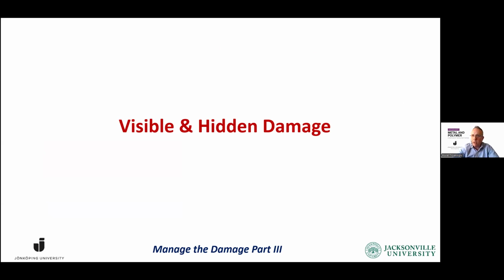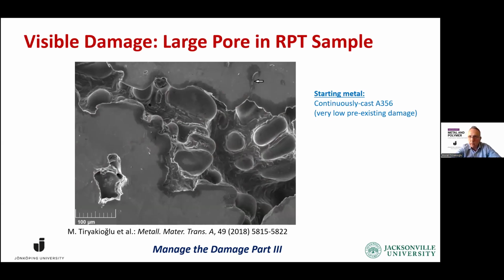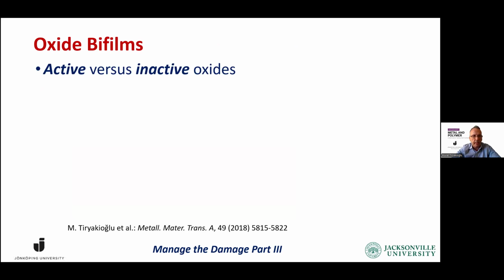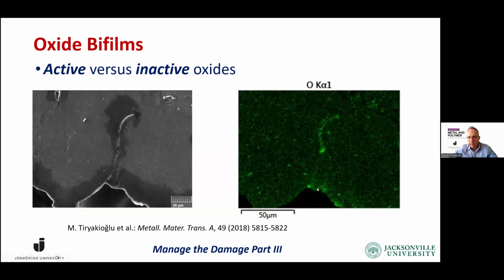So this occurred to us some time ago, and I want to give you an example of the origin of our thinking. We were measuring the entrainment damage, both surface and air. We started with a very good metal, continuous cast A356 with very low pre-existing damage. We measured that, and we were looking at our RPT specimen. And of course, the first thing that you see is this large pore. That's good, because we were looking for pores. But then this curious feature that you may see here attracted my attention, and I asked, well, what is that? And when we turned the X-ray mapping on, you can see that this is for oxygen. This is clearly a folded oxide hiding between the dendrites near the pore.